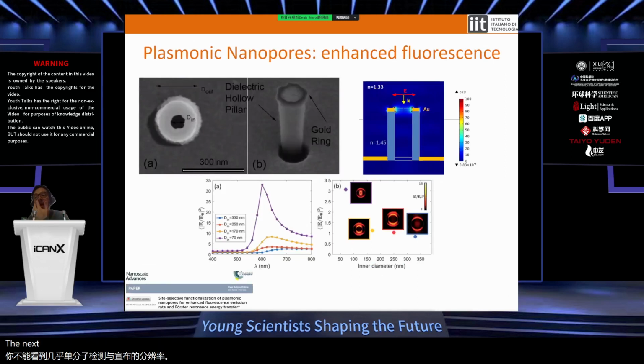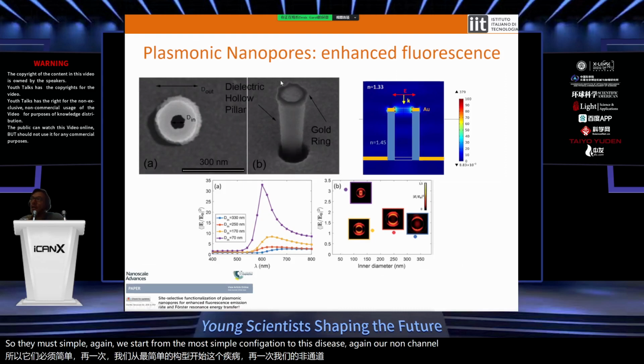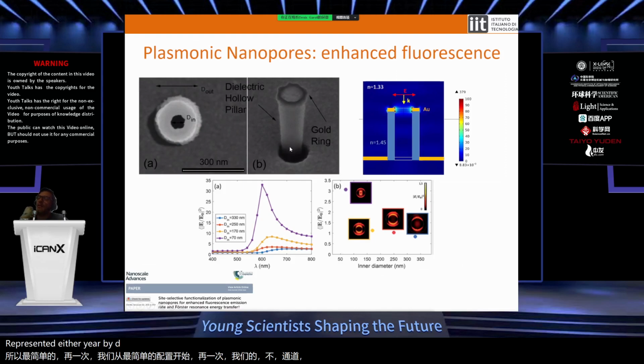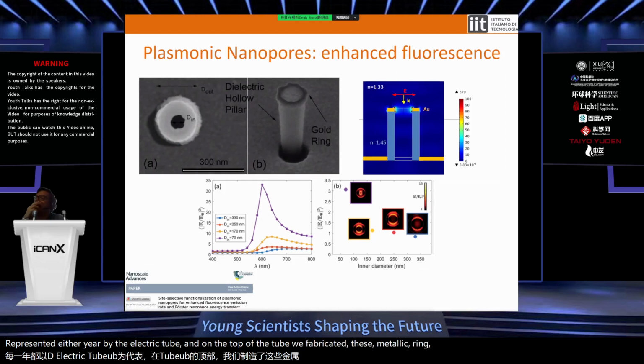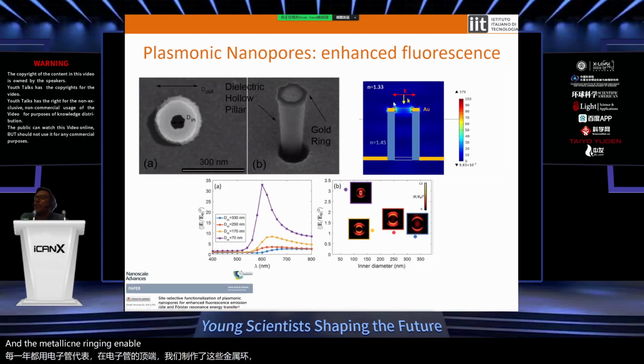The next step was to go towards the 3D configuration. Again, we started from the most simple configuration. This is again our nanochannel, represented here by a dielectric tube, and on top of the tube we fabricated this metallic ring. The metallic ring enabled us to confine the field inside the pore. Obviously, if you reduce the size of this ring, you can increase the confinement, consequently increasing the electromagnetic field.